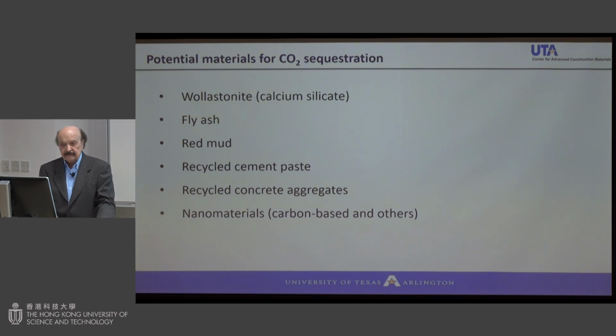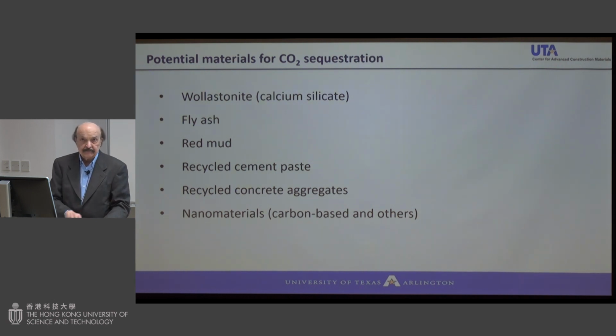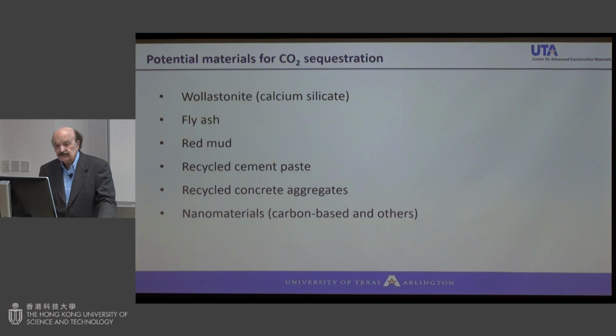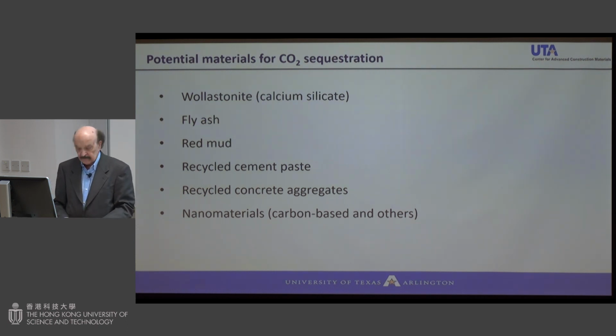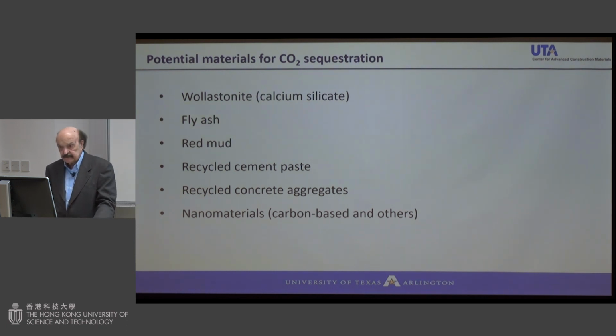Wollastonite, I mentioned, this is the company Lafarge and Solidia, and that's CAS, calcium silicate. Fly ash certainly, especially high calcium fly ash. And high calcium fly ash is not normally preferred as a pozzolanic material, but it's very good for carbonation. Red mud, I talk a bit about it. Recycled cement paste, recycled concrete aggregate, and then finally some very recent work we have done with nanomaterials.